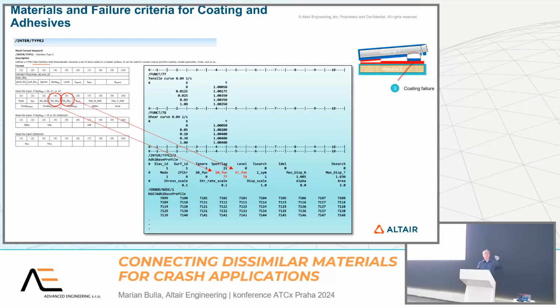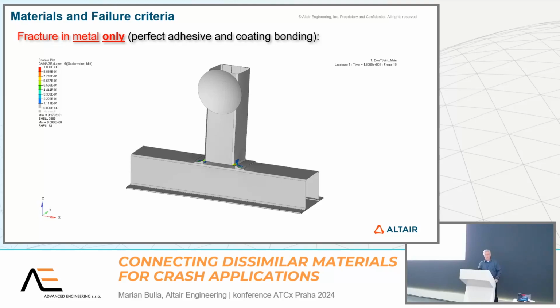How to model it? The thickness of the coating is very, very thin. So even with today's methods, we cannot model it with elements. So we can use a tied contact interface with definition of failure in normal direction and shear direction. So you add a tied interface between two layers of elements which do not have the same mesh, a different mesh. And in between, you model your coating with an interface. So once you do that, you have the possibility to model material and fracture for the base metal, which must not be metal, whatever, polymer, the adhesive, and between adhesive and your material, the coating by contact interfaces.